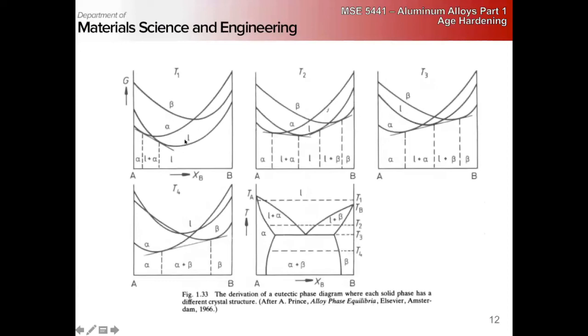So if we look at the free energy curves, if I'm at this eutectic composition, I'm pure liquid. I'm in between the common tangent. So if I'm in this region, I'm alpha, liquid plus alpha, liquid, liquid plus beta, beta. Essentially, the eutectic point is where I have a common tangent across all three phases. This only happens at exactly one temperature. I need all three points to be collinear. And if I follow that down, what it means is I stay liquid. This liquid region gets narrower and narrower as I lower the temperature. Eventually, I hit the eutectic point. So as I come down, I'm liquid, and then I spontaneously freeze into alpha plus beta.